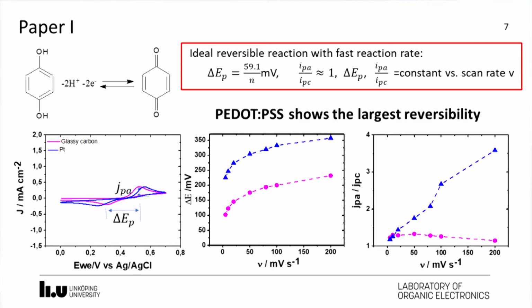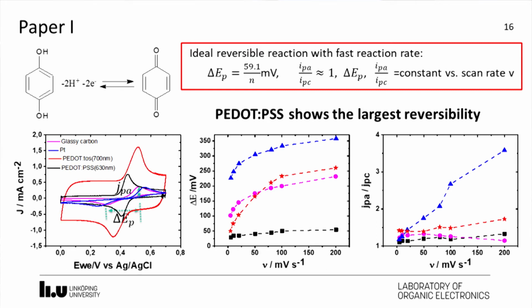On glassy carbon electrode, we found that it is quite irreversible because the peak-to-peak separation, even at a low scan rate, is quite high, around 100 millivolts, even though the current ratio was almost 1 and independent of scan rate. The reversibility was even less on platinum electrode because of higher peak-to-peak separation and also the dependence on scan rate. And a little higher reversibility was found on PEDOT:TOS because the peak-to-peak separation was smaller at low scan rate. Here the current ratio is also independent of scan rate, but the peak-to-peak separation increased dramatically with the scan rate.